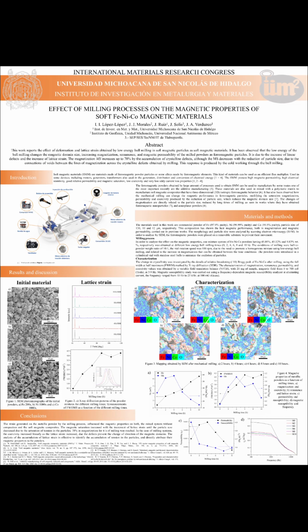It is observed that from 2 hours of milling, the nickel and cobalt particles began to flatten and coat the iron particles. The iron particles are deformed in the same way as those of nickel and cobalt. The 8 and 10 hours of milling do not show a considerable change in particle size. Both nickel and cobalt particles are accumulating around the iron particles.